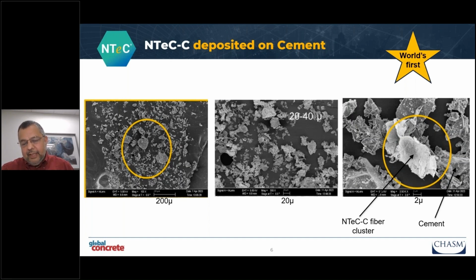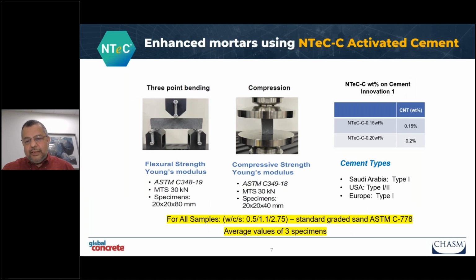So what this does is you have a specific surface area of cement of roughly 100 to 200 square meters per kg, supplemented by something which has a similar specific surface area, except it is square meters per gram, 100 to 200 square meters per gram. And suddenly you're creating a much, much higher surface area, even with dosages as low as 0.15 or 0.1%. And so we took that composition of 0.15 to 0.2% and went back to our university partner with three kinds of cement, one from the US, one from Europe, one from the Middle East, just to get some global mix into the game, and went through the regular ASTM tests.